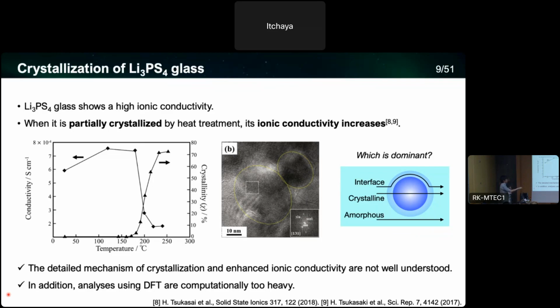And they have performed the microscopy measurement, and they found some connected crystalline nucleus like this, and they deduced that the mechanism behind this increase is like a percolation mechanism, but which is not very established. And there are other possibilities like the interface.